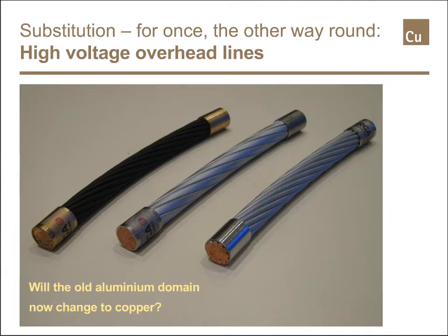These conductors are actually made of a so-called copper microalloy. There is much less than 1% of alloyed elements in there, so that the conductivity remains considerably higher than that of aluminium, but the material is very hard, has a high operating temperature and a low sag, and therefore can be operated at temperatures up to 180 degrees Celsius, while aluminium goes only up to 80 degrees Celsius. Now, it is not normally that we produce higher losses, but in those situations where such a high load, a peak load, occurs only 100 hours a year or so, the copper conductor is really a solution where an extra line cannot be installed.